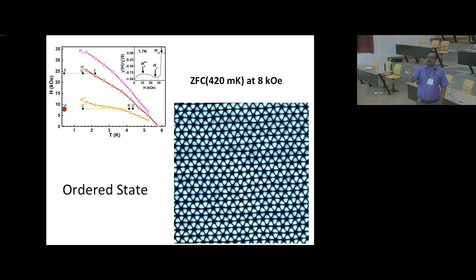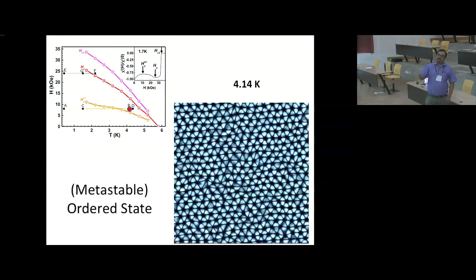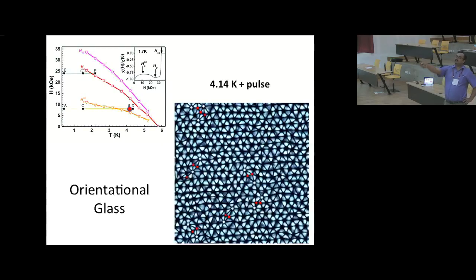So I prepared the state at point A here. It's a perfectly ordered state. Then I heat it to point B. So I have crossed this phase boundary. But still it is topologically ordered. I don't see defects coming in. However, this is a superheated state. And how do I know it's a superheated state? I apply a small magnetic field pulse, I shake it. As soon as I shake it, I see that I have dislocations that come in.